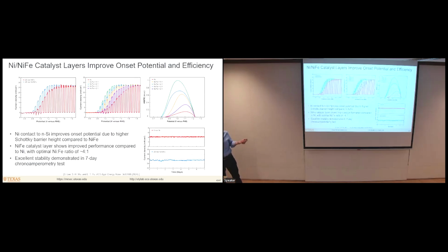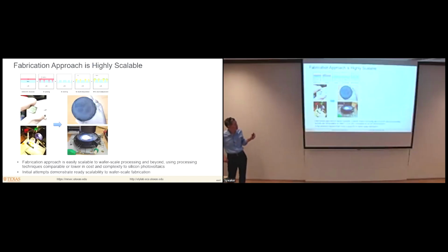If we do that, we can see that indeed nickel in contact with the silicon, compared to nickel iron, gives us better turn-on characteristics, and the optimum ratio of nickel to iron is roughly 4:1. We get large increases in the efficiency and still very good stability. What's really interesting about this is that all of the unit processes that are required to make these structures are really quite simple, low cost, and easily scalable. They're similar in complexity, maybe even a little less complex than what is typically used to make silicon solar cells, which we know are very low cost and massively scalable.